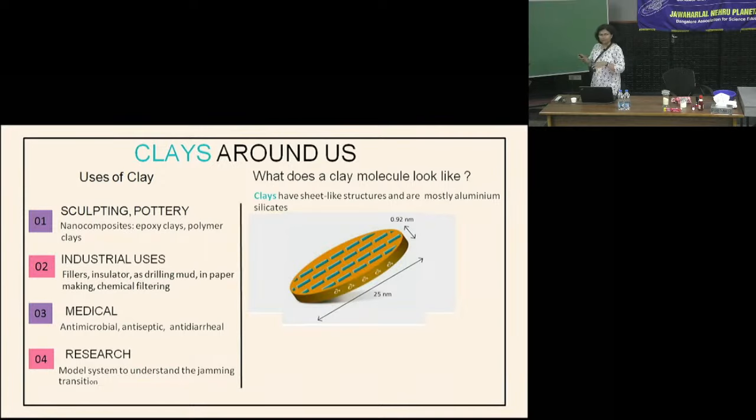Please, you can interrupt me. This is what it looks like. It has unlike charges on the surface and on the edge, and this happens only when you put the macromolecule in water. When you put many of these macromolecules in water, the positive charges of the rims interact with the negative charges on the surfaces through something called a screened electrostatic attraction, okay?